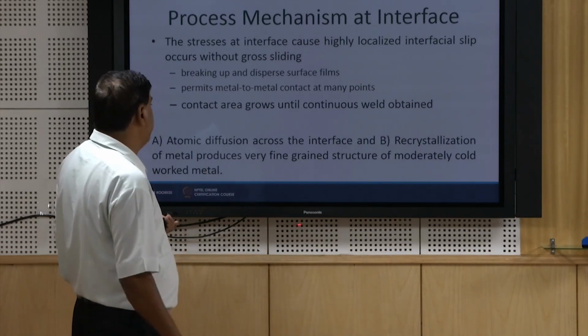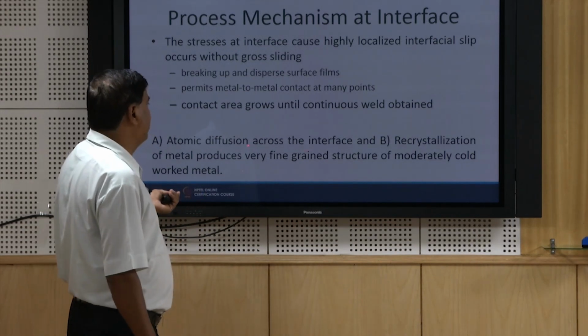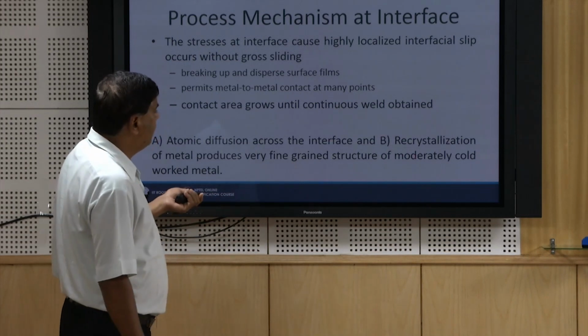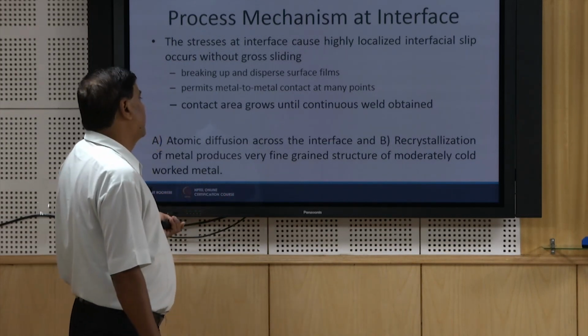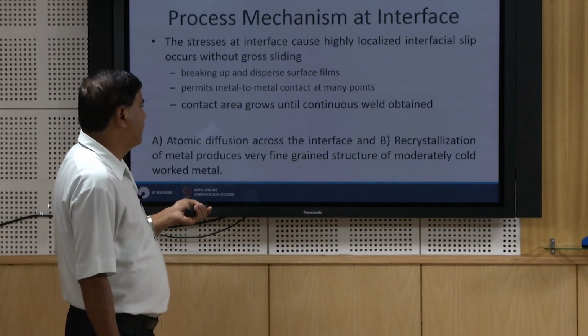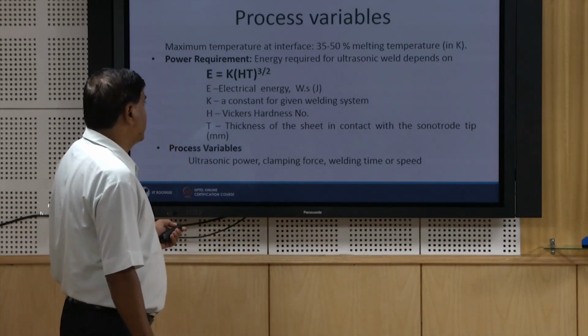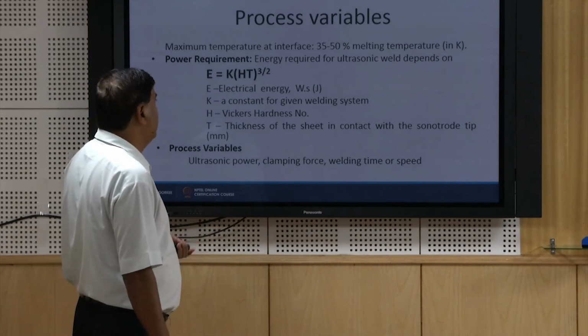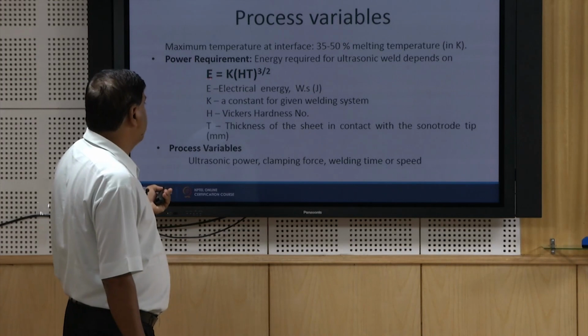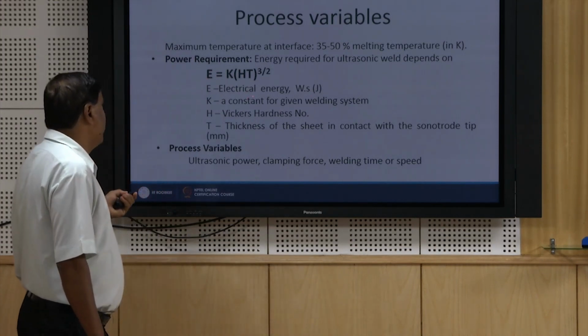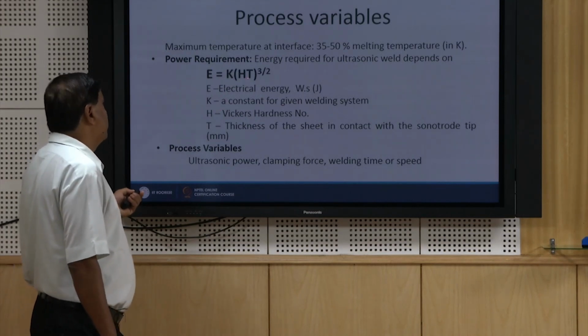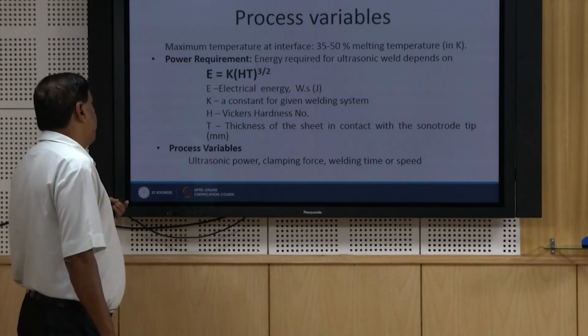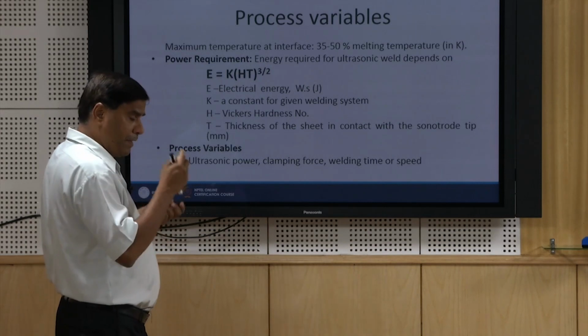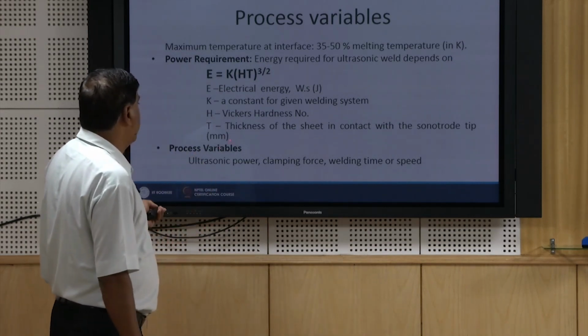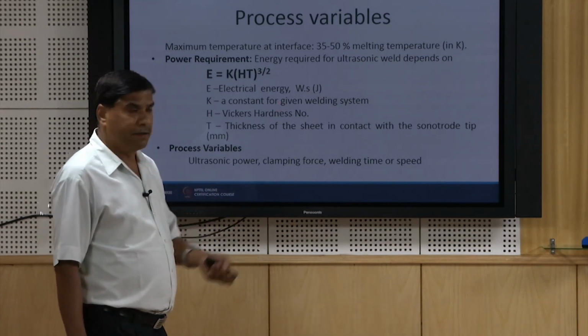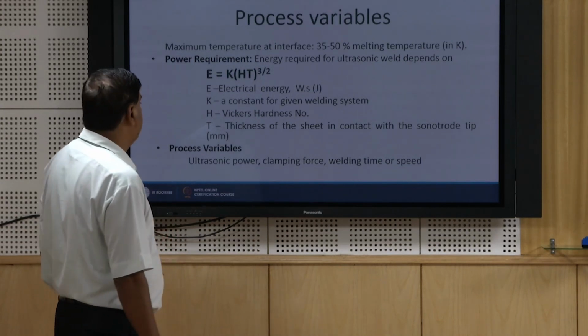which in turn grows the size of the weld being made, and in this process itself diffusion at the interface takes place, and at the same time frictional heat causes enough rise in temperature for recrystallization to take place, that in turn defines the grain structure. As I have said, the success of the process depends on how effectively we can supply energy, and how much energy we need to supply. So, the electrical energy to be supplied in the course of the process is a function of the hardness of the material, Vickers hardness, and the thickness T, and this will govern how effectively a sound weld joint will be made. So, as per the thickness and the hardness of the material, we need to supply different amounts of energy for the ultrasonic welding process.